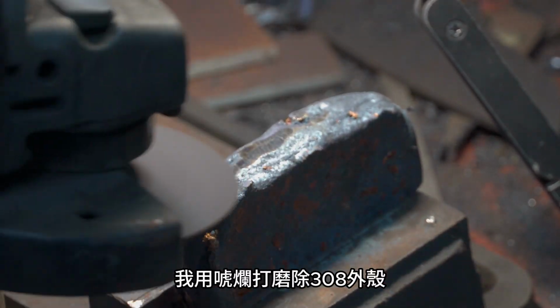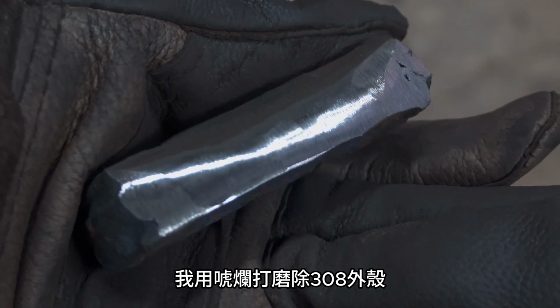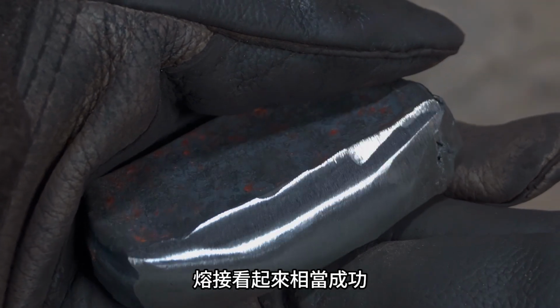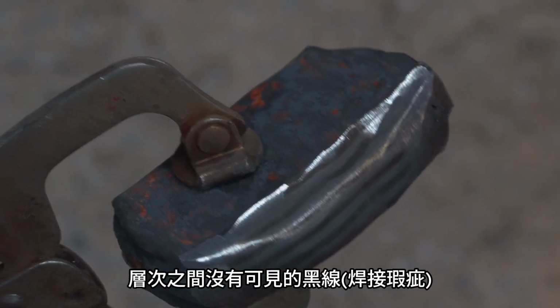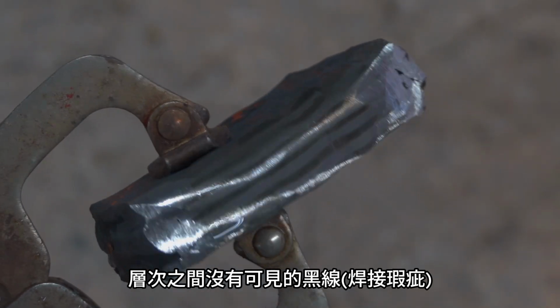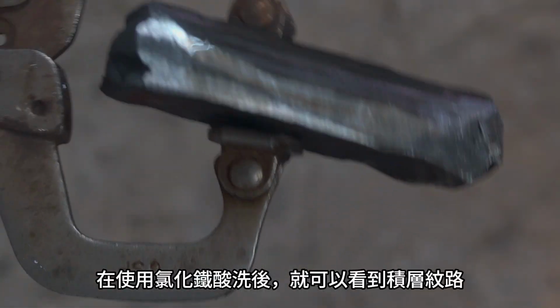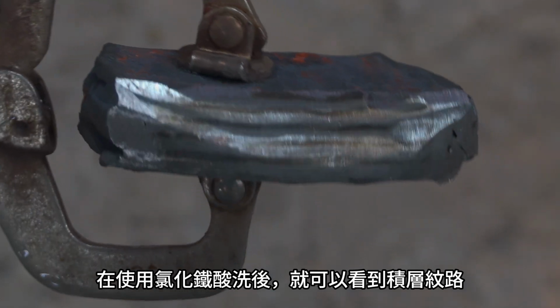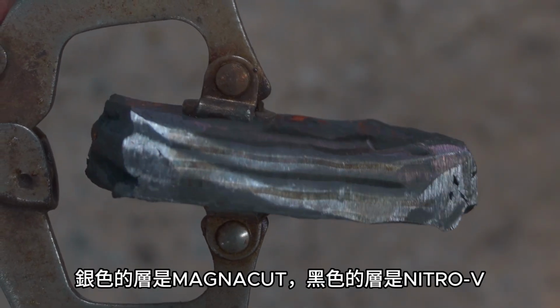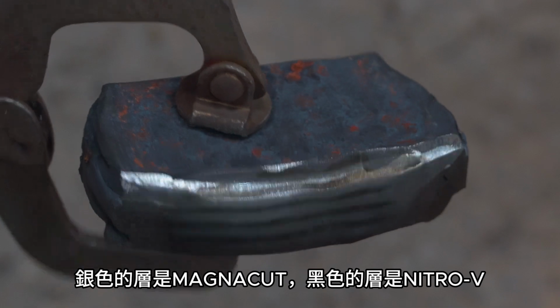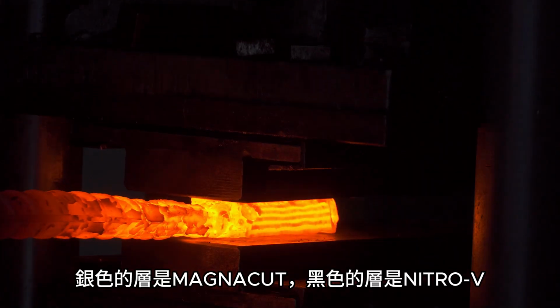I used an angle grinder to remove the 308 shell, and it looks like the weld turned out pretty well. There are no noticeable black lines between the layers. After etching with ferric chloride, the layer pattern becomes visible. The silver layers are MagnaCut, and the black layers are Nitro-V.